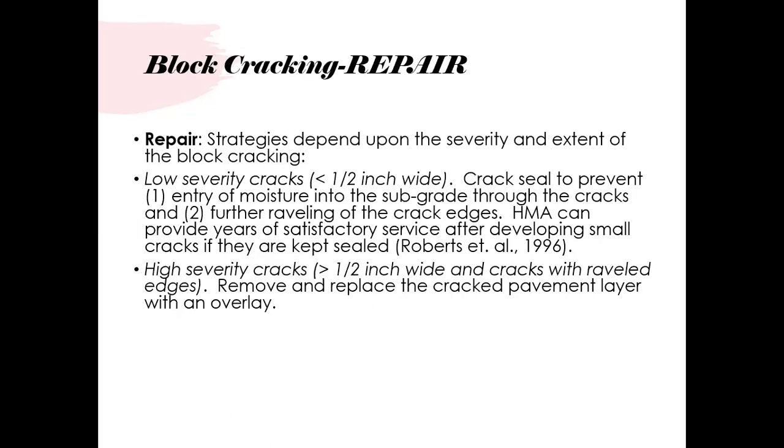Another type of crack is called block cracking, and again the repair can be applied at two levels depending upon severity. By severity, I mean if the width of the crack is less than half an inch, it will be categorized as a low severity crack.